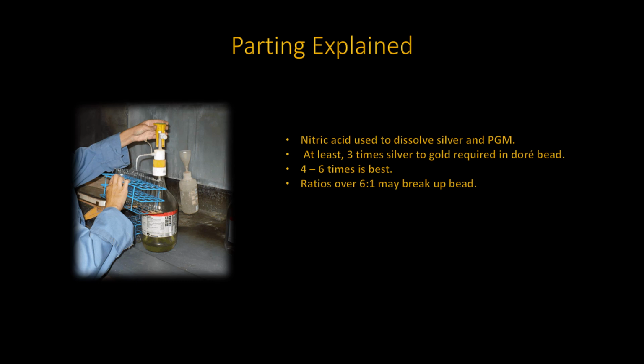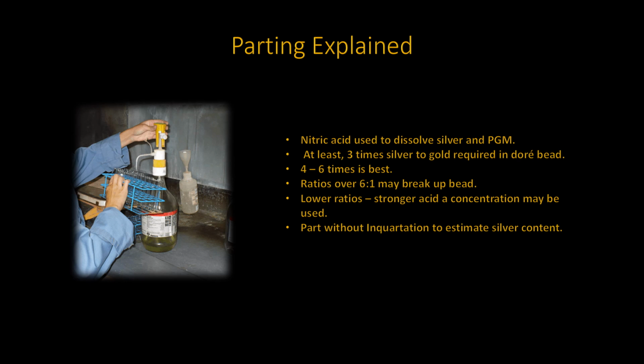With larger concentrations of silver in the bead, special precautions must be taken. With concentrations of 6 to 1 or greater, the bead will break up into smaller particles. The parting process must be manipulated in a way that results in the particles being left in a single mass. The strength of the nitric acid solution is dependent on the silver to gold ratios. The lower the ratio, the stronger the solution that may be used without having the bead break up into smaller particles. It is best to conduct an initial parting without inquartation, which will be explained in an up-and-coming slide. This is done to estimate the amount of silver in the bead.